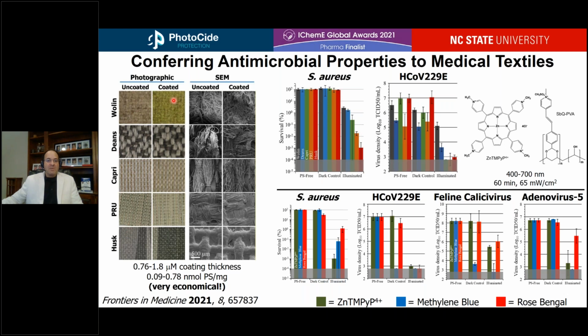In the SEM images, you can see the uncoated fibers versus the spray-coated fibers, again, using a spray coating that's a bicomponent mixture of our photodynamic drug and our photocross-linkable polymer. And based on those images, what we have been able to establish is that our coating thickness is relatively thin compared to the fibers. It's only about a micron or so.